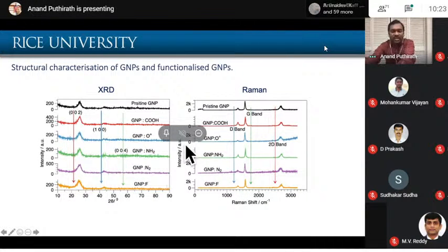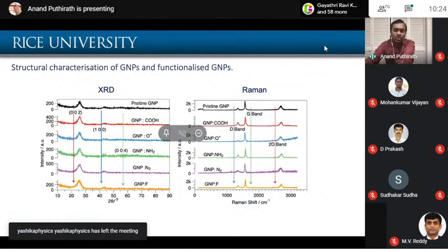And we characterized it. There are several techniques to characterize materials, starting from XRD, Raman. Raman is specifically good for 2D materials, because as soon as you confine to 2D, the in-plane vibrations dominate over the out-of-plane phonon modes, right? So you can identify whether your system has a two-dimensional confinement or not, where you will see the in-plane vibration phonon modes intensified. And if you look in 2D material research, Raman is the major tool to characterize them.